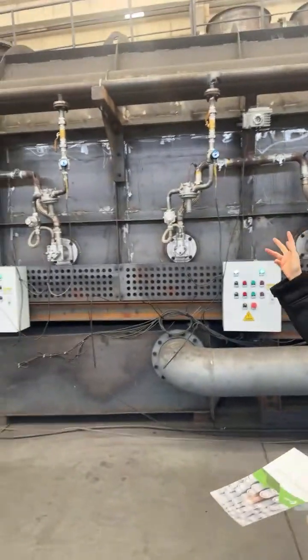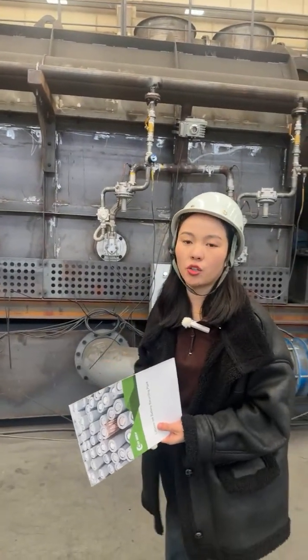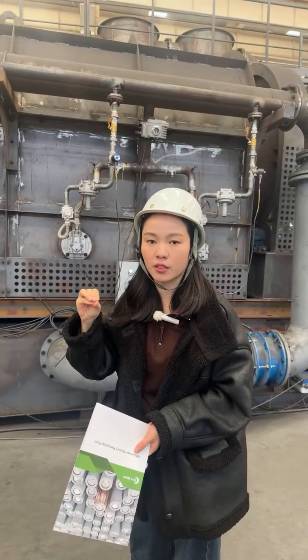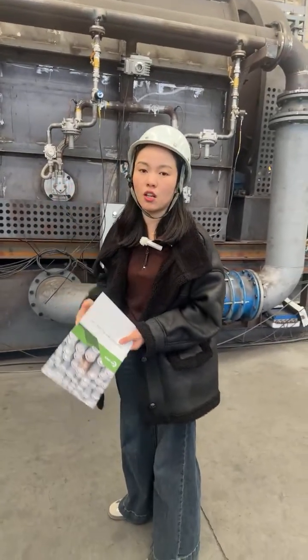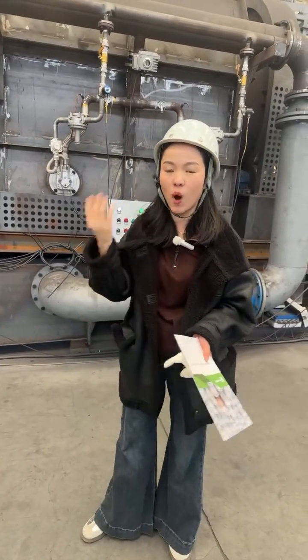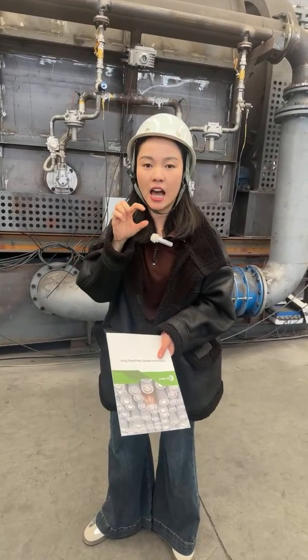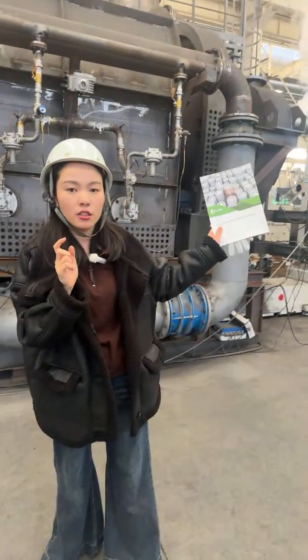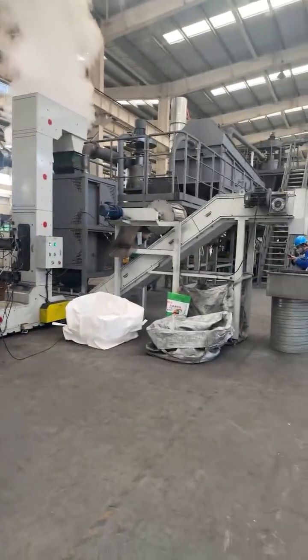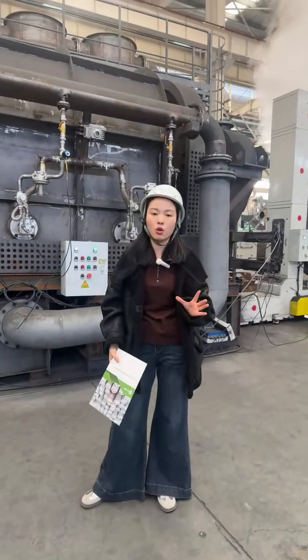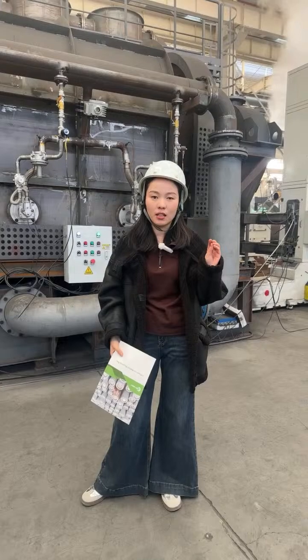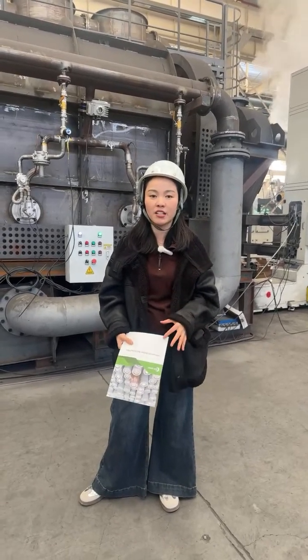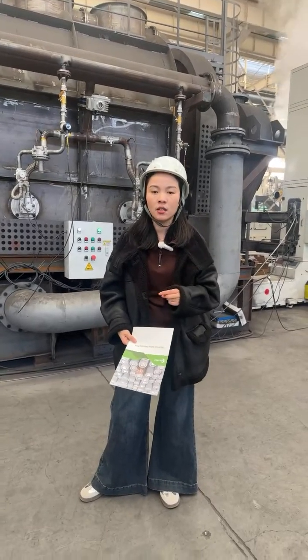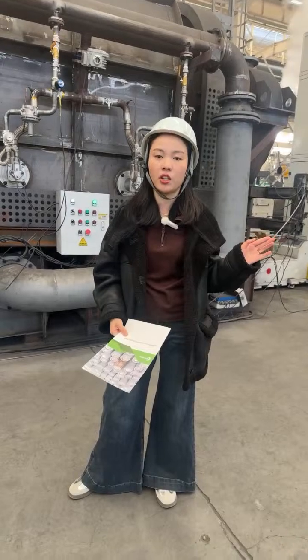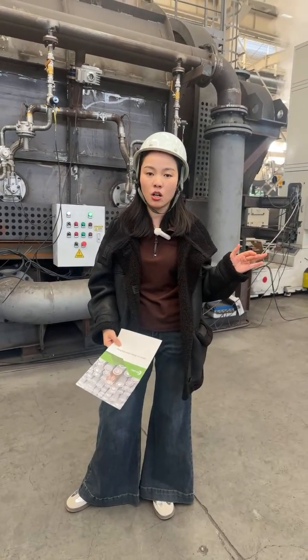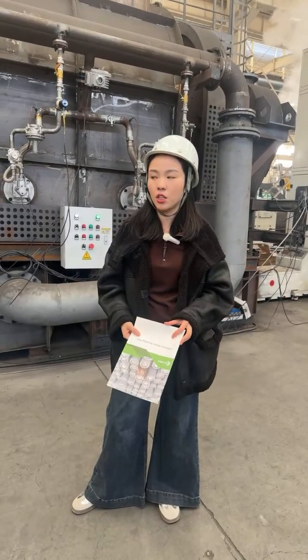Actually, there are three different functions of this carbonization furnace. First of all, the electrolyte inside the battery is liquid. It's very sticky. If you don't use the furnace, the liquid will cause the black mass to stick heavily on the copper and the aluminum. So in the following separation stage, it's very difficult to separate the black mass. There will be a lot of black mass still stuck on the copper and aluminum and even the battery casing. When you separate the battery casing, the battery interiors, and you separate the copper and aluminum, a lot of black mass will be wasted, will be lost.